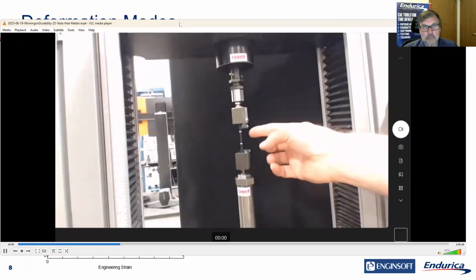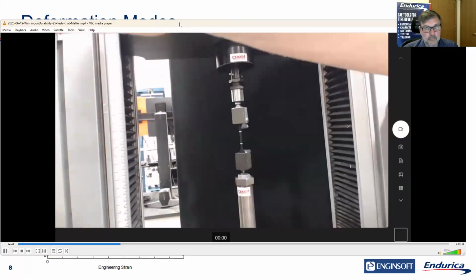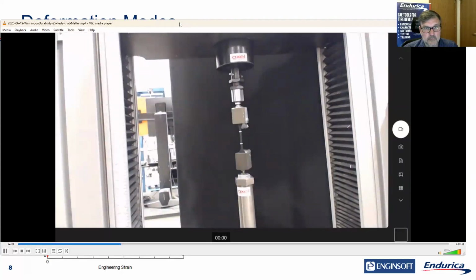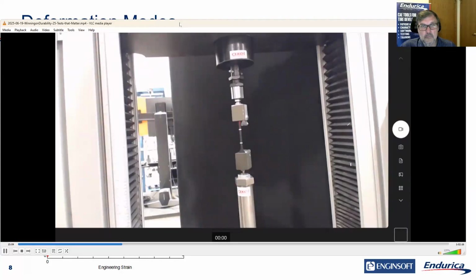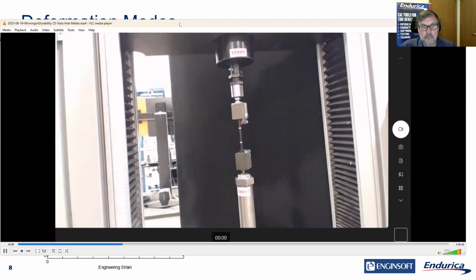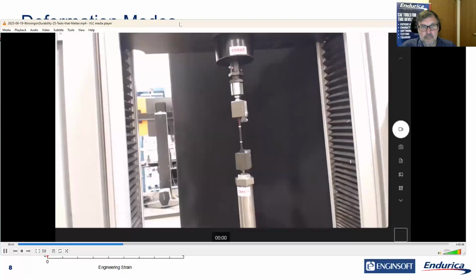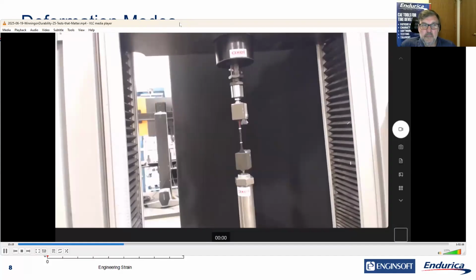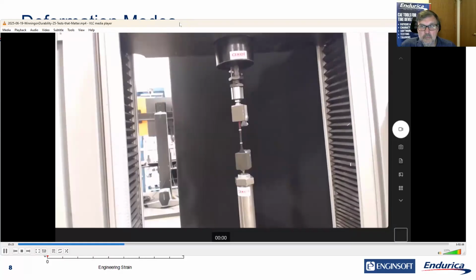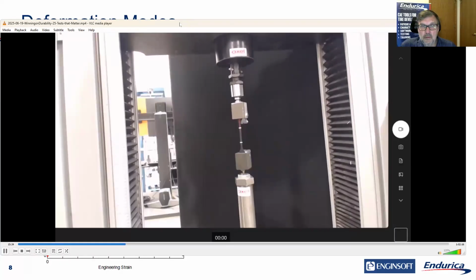So here we have our specimen in the machine. It's got the two stickers. Laser extensometer is going to measure the strain. So right now, I'm just going to start a test running. We're going to look at the screen. Then, because we have a lot of material to jam into an hour, we're not going to stay too long with that. So right now, I don't know if you can tell, but that crosshead is moving. And what I've done is I've stretched to 30%. Now I'm unloading back to a near zero stress. And I'll talk about why that's important in a second. The really important thing is that we have put the rubber into a state of tension so we can write math around it.